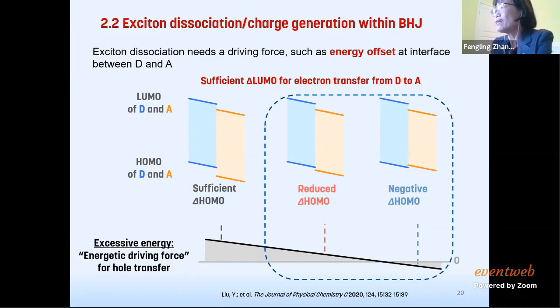The far right one is even worse, because in this case we can see it's energy transfer. It's not charge transfer, because the exciton energy is in the band gap of the donor material. Then we have questions. According to the traditional opinion, this kind of combination should not work at all, because it's not charge transfer, it's energy transfer. However, with these new non-fluorescent acceptors, even when the HOMO level offset is quite small, we can still get quite efficient cells. So in this case, we compare two situations.